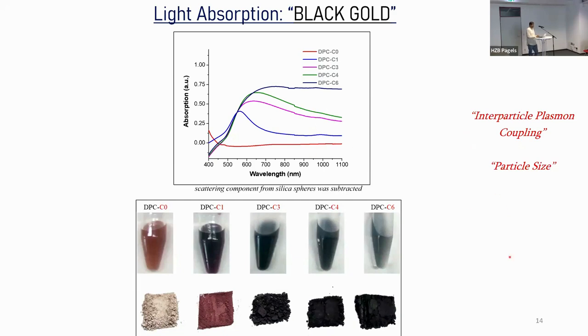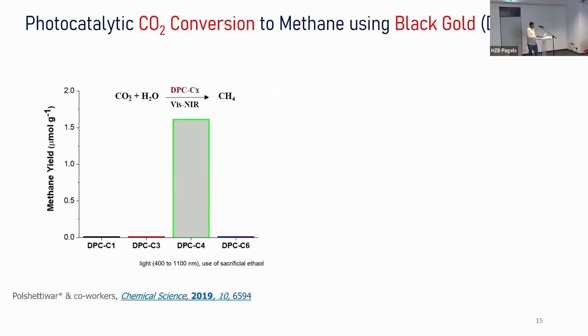So looking at this data, we were very excited. We said, okay, now we got a material which harvests the entire solar spectrum, so it should show good photocatalytic activity. So we tested this for a simple reaction, CO2 plus water to give you methane, a photocatalytic CO2 methanation. And now you see this DPC4, which is a black gold, gives you around 1.5 micromole per gram of methane yield, which is 10 times better than if I use a 10 nanometer gold particle. So clearly indicating that the plasmonic coupling does play a role, and you can increase the catalytic activity.